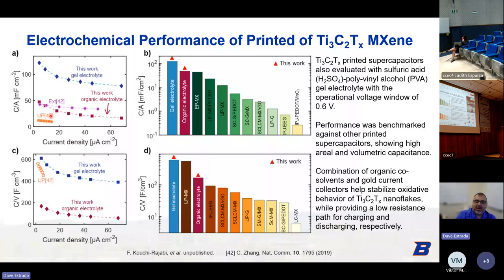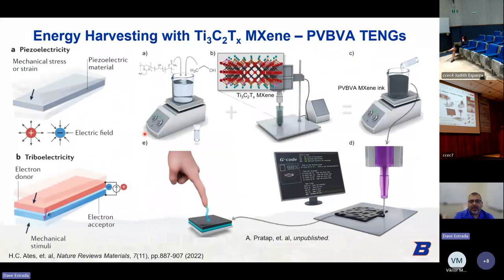And then when we do the volumetric, the inkjet printed work that was reported in this paper by Valeria Nicolosi's team, that performance goes up, but our gel electrolyte still has more charge storage capacity. And so then we can also look at other printed devices in the literature and see that these MXenes and the gold current collector offer a route towards really high performance supercapacitors.